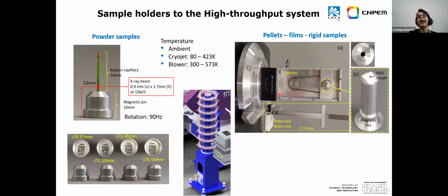Another sample holder that we have is for samples that are not produced in powder form. So they are pellets or films or rigid samples. Our pin has this neck, and on the bottom we have the identification system. The sample is placed here and connected to the sample holder using a carbon double-sided tape. You put it here, the beam comes from the back of the sample holder to this point here, and it's where the X-ray beam interacts with the sample.